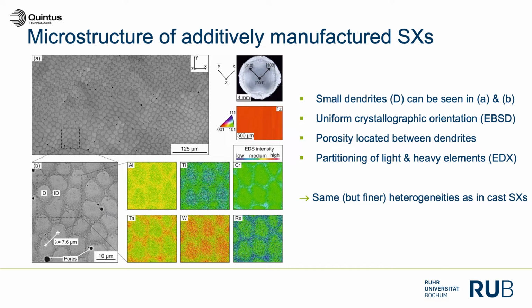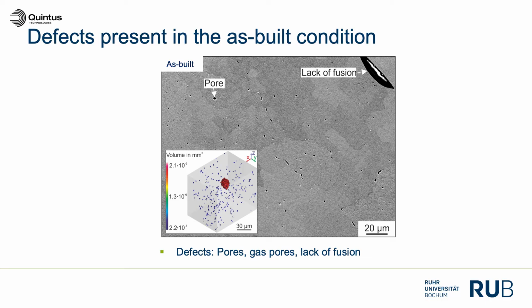This is really impressive. And the very interesting fact here is that everything is on a much smaller scale, because the solidification rates are much higher than in conventional castings. This leads to a very fine and uniform microstructure. However, it still contains all the microstructural defects we also find in conventional cast microstructures. We have porosity, we have also gas inclusions, we have small-scale chemical inhomogeneities, and this means we still have to post-process the materials, and we can also obtain cracks during processing.